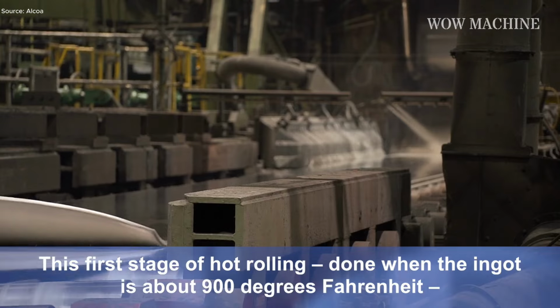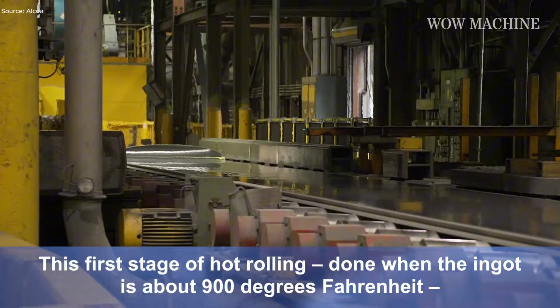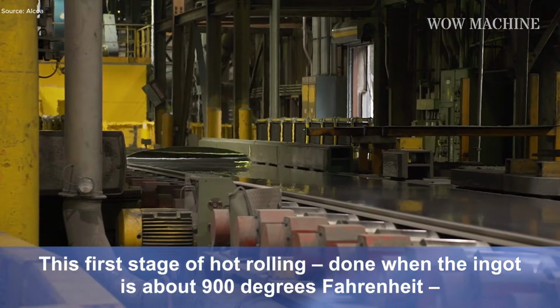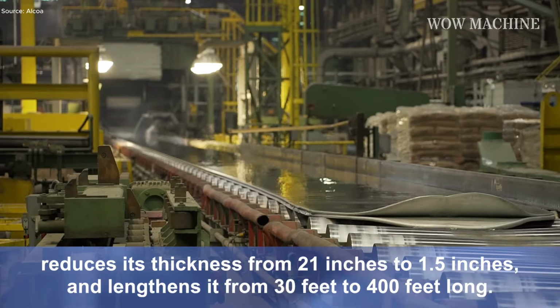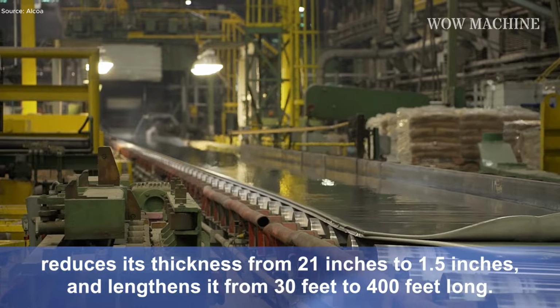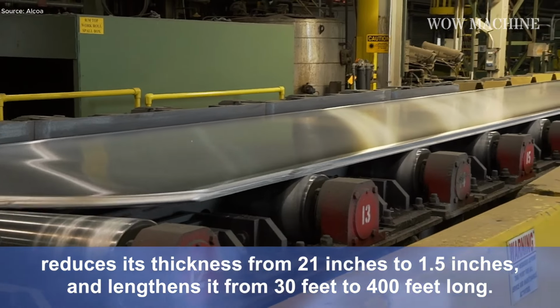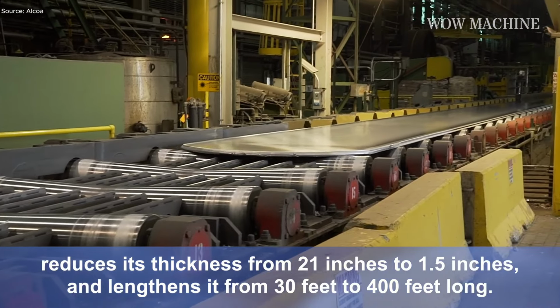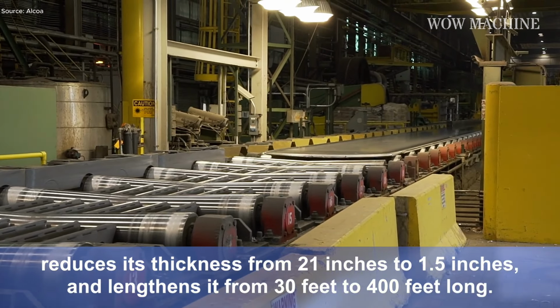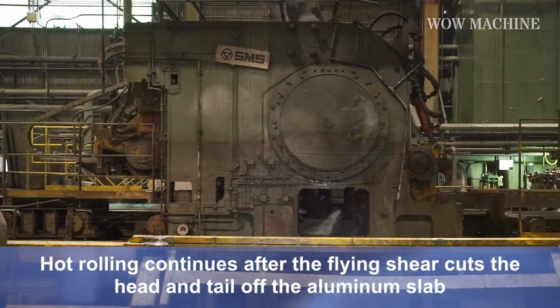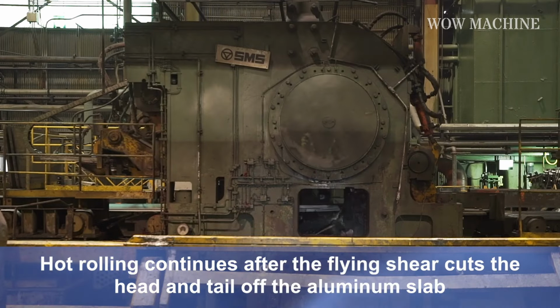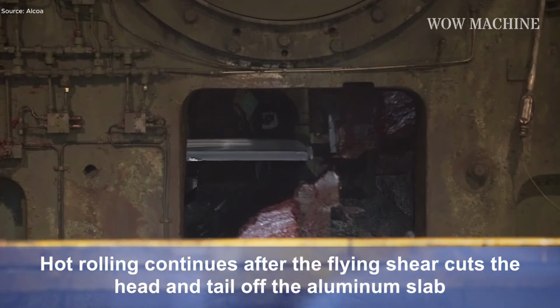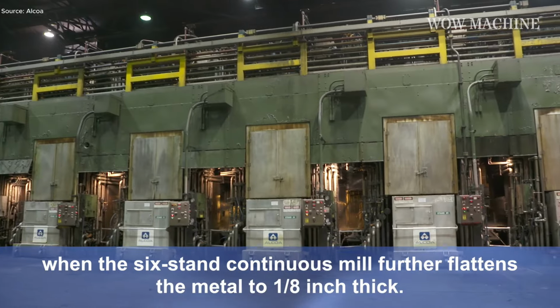The hot rolling stage begins at the reversing mill, where two 7,000-horsepower motors drive the rollers to reduce a 40,000-pound ingot from 21 inches to 1.5 inches thick, simultaneously elongating it from 30 feet to 400 feet. After the flying shear removes the head and tail, the continuous mill flattens the slab further to 1/8 inch, producing a coil about a mile long.